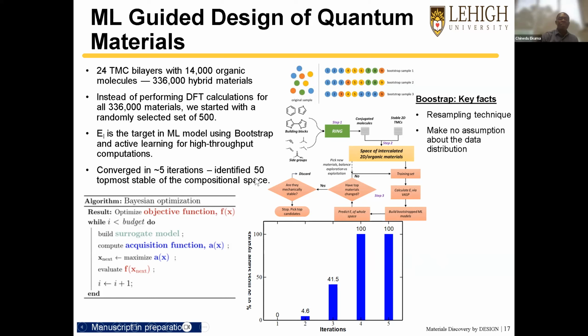Our target is to identify the 50 top most stable structures from our compositional space. Once this happens, we stop. Those are the 50 top structures that we want, and they are the most stable within our 336,000 hybrid structures. As you can see, instead of doing 336,000 calculations, you roughly do about 2,000 or 2,500 independent DFT calculations, which is a fraction. And because the bootstrapping technique makes no prior assumption about the data distribution, we are able to capture the overall trend with respect to which structures are stable or not.